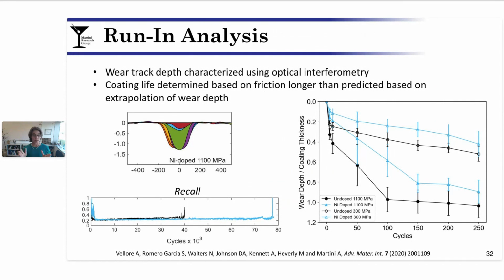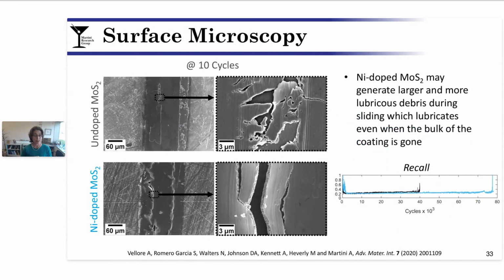And what you can see on this plot, which only goes to the first 250 cycles, is that even within those first couple hundred cycles, we've already reached, in some cases, the very bottom of the coating. This appears to be contradictory with the many thousands of cycles that we found for wear life based on friction. We also performed some microscopy of the early cycle results and found some differences in morphology between the nickel-doped and the undoped coating. So this suggests that this material or debris generated in the first few sliding cycles may be incredibly important as we think about why the wear life might be longer for the nickel.